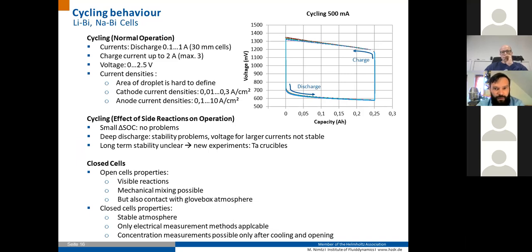We had most experiments with sodium bismuth cells in the beginning, and later switched to lithium bismuth cells because, as I said, the experimental behavior of lithium bismuth is much better due to lower solubility, and most of the numerical experiments or numerical simulations were also done with the lithium bismuth because there is much more literature available on these electrode combinations.